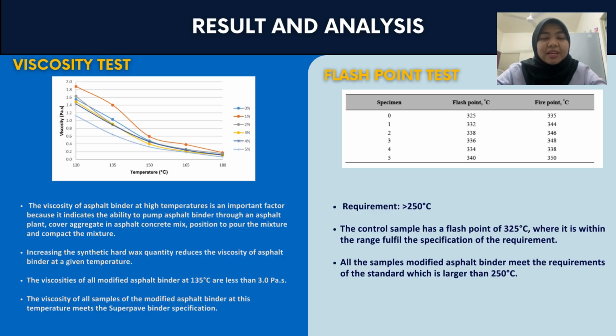The viscosity of asphalt binder at high temperature is an important factor because it indicates the ability to pump asphalt binder through an asphalt plant, cover aggregate in the asphalt concrete mix, position to pour the mixture, and compact the mixture. Increasing the synthetic hard wax quantity reduces the viscosity of asphalt binder at a given temperature, which are 120 degrees Celsius, 135 degrees Celsius, 150 degrees Celsius, 165 degrees Celsius, and 180 degrees Celsius.